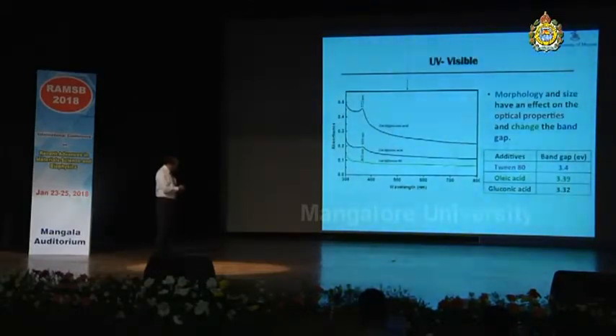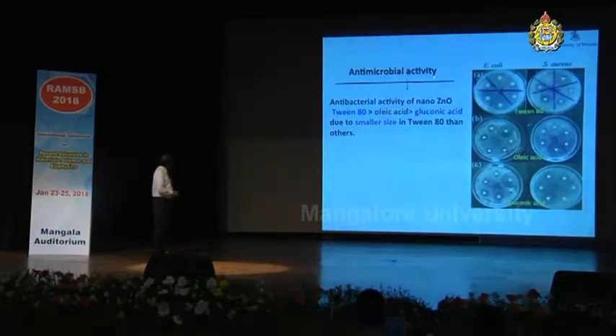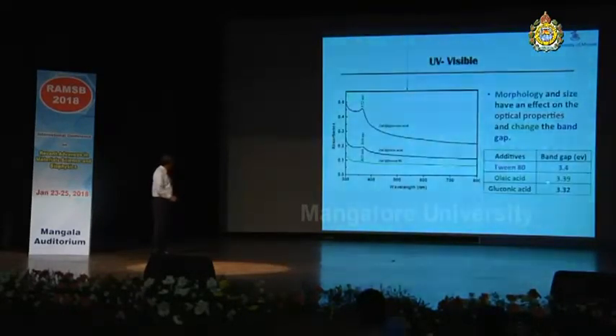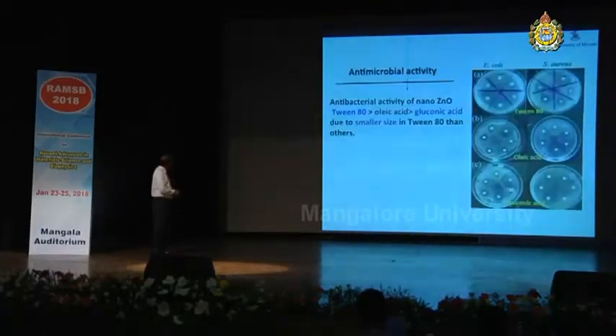UV visible spectra of these different zinc oxide obtained with different surfactants like Tween 80, oleic acid, gluconic acid, and the band gap energy varies accordingly depending on the surfactant. And antimicrobial activity of zinc oxide, I have compared these three samples which I have shown here. So you can see Tween 80 showing greater than the zinc oxide obtained with oleic acid, and that is much greater than the gluconic acid.